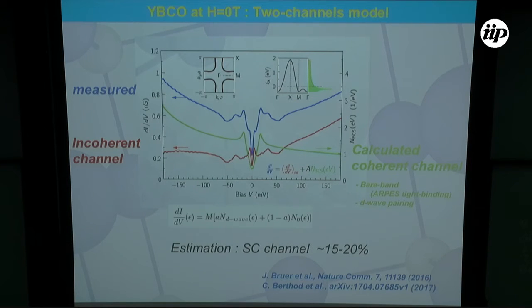So we had to consider a very simple model where we consider 2 parallel channels. The 2 channels are added in order to provide the measurement. The one channel is the one which we call the incoherent channel, which involves all these subgap state features and a number of other features from the spectra. The second channel is the purely superconducting channel, which can be calculated considering a bare band structure with realistic coefficients and D-wave pairing. And a weighted sum of these two channels will provide the measurement. Our estimation gives a contribution of 15 to 20% only of the superconducting channel.